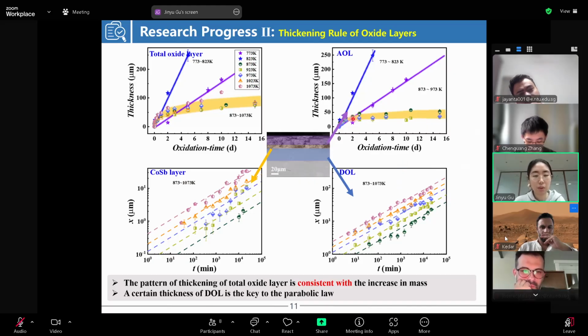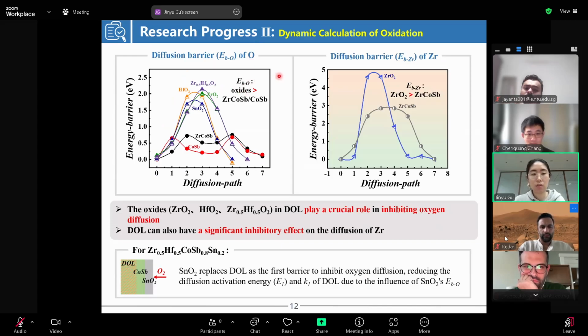Through the analysis of the thickening rule, it was found that the pattern of the thickening of the total oxide layer is consistent with the mass gain, and a certain thickness of DOL is key to the parabolic law. And first principles calculations of dynamics were conducted. The diffusion barriers of oxygen and zirconium in oxides are much larger than in other compounds like zirconium cobalt antimony and cobalt antimony. It can be concluded that oxides in DOL or outside the cobalt antimony layer played a key role in inhibiting the diffusion of oxygen and zirconium.